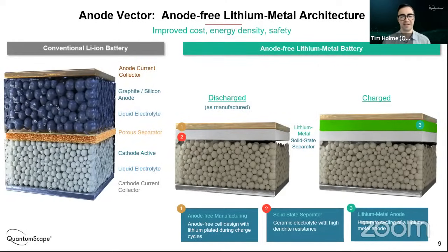On the left-hand side, you've got a schematic of a lithium-ion battery. You'll have a host material that includes graphite and often silicon, a porous polymer separator, and a cathode material. This could be LFP, or other nickel-containing chemistries like nickel cobalt aluminum or nickel manganese cobalt materials, and the whole thing is immersed in a liquid electrolyte that conducts the lithium ions back and forth. Lithium, of course, is stored in the anode when the battery is charged, and as the battery discharges, lithium moves down into the cathode. The anode-free lithium metal battery would replace this anode host material with nothing in the as-manufactured state. Then all of the lithium that's present in the cathode as manufactured plates on the first charge and becomes a solid lithium metal anode. That is the lithium that gets cycled back and forth as the battery charges and discharges.